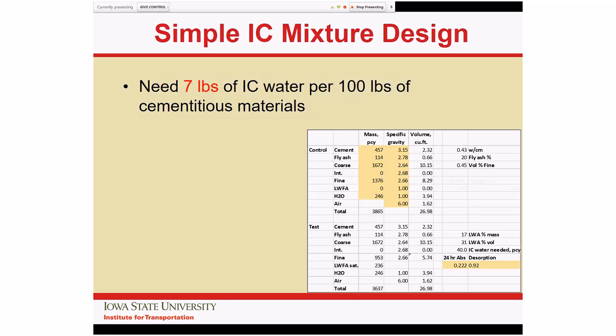But basically, if you know the properties of the aggregate that you have, so if you look at the bottom right hand, there it is, there's my mouse, if we know the absorption and desorption of the lightweight fine aggregate that we're providing, it's a pretty simple calculation that comes back and says you need about, in this case, 230 pounds of lightweight fine material to replace the conventional fine aggregate. That's enough to get a rigorous set of internal curing. So the quantities are not great.